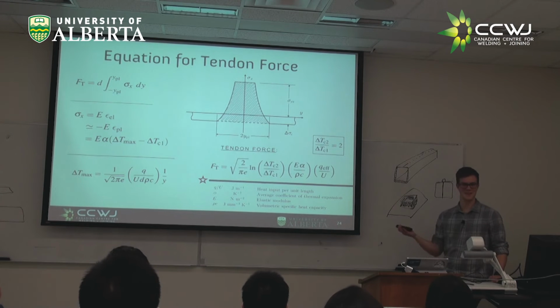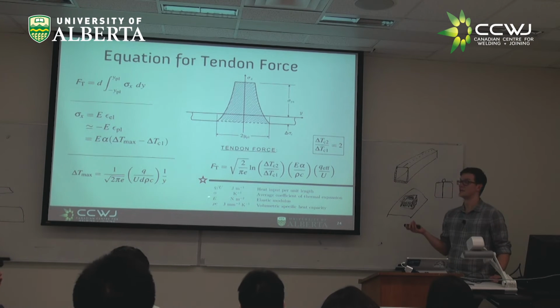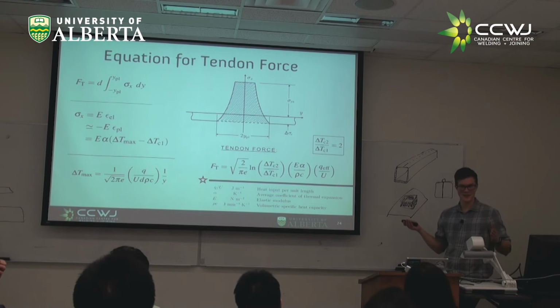Now I say not necessarily as a bit of a catch-all because we made some assumptions here. We assumed that we're elastically perfectly plastic. We didn't deal with phase transformations. We addressed that as we get to really high strength materials, some of those effects might start to come into play. Interestingly though, if you imagine you've got phase transformations, typically you actually end up expecting lower stresses in the region. So maybe high strength materials might actually have lower stresses.